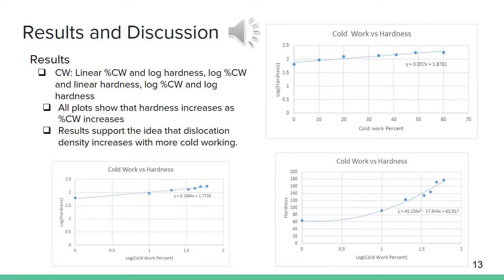In addition to a linear plot, 3 other graphs were also generated. Going clockwise around the slide: linear % cold work and log hardness, log % cold work and linear hardness, and log % cold work and log hardness. All plots show that hardness increases as cold work increases, with generally positive trends. These results support the idea that dislocation density increases with more cold working.